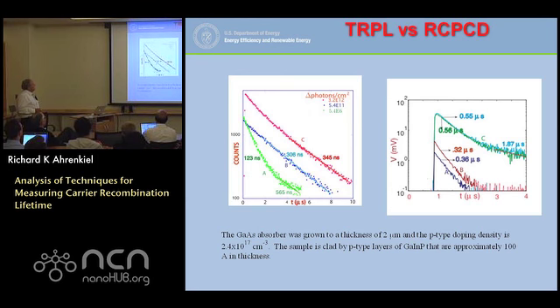TRPL versus RCPCD, which I'm calling resonant coupled photoconductive decay because of the coupling to this resonance. So this is a gallium arsenide thin film grown at NREL, 2 microns, probably Dan Friedman's group, that was passivated with gallium indium phosphide, which is lattice matched and is an excellent ternary passivation agent for gallium arsenide. We measured this by TRPL and by RCPCD, the same sample. These are the photon fluxes. I had the photons for the TRPL, not for the RCPCD, but they're larger here. And you see roughly, it's around 300 nanoseconds.